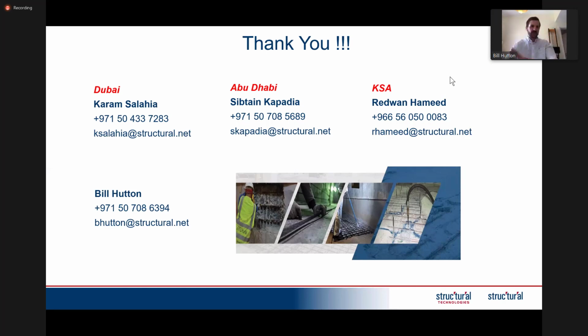Yeah, that's a good question. We didn't really talk about QA/QC on cracks. But one way to ensure this, say if you have a raft which is 800 millimeters thick, and you've got a through and through crack where you've got groundwater coming through, is ensuring you have a good technique. If you're doing interception grouting, you need to make sure your drill hole is positioned in the right place and drilled at sufficient angle.